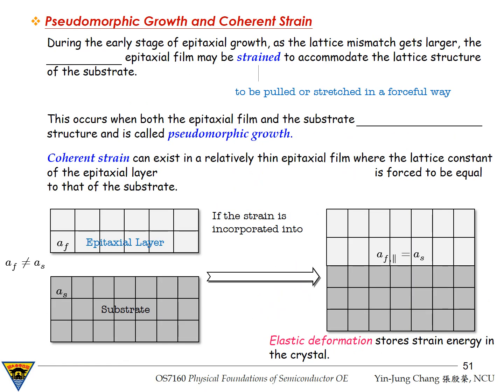Before delving into graded epitaxial growth, we need to fill in some gaps here, including pseudomorphic epitaxial growth, strain, and misfit dislocations. So far, we have discussed the ideal case of lattice-matched epitaxial growth, where the lattice constant of the epitaxial film is equal to that of the substrate. In that situation, the atomic rows line up perfectly, and no strain is introduced at the interface. But in many practical semiconductor systems, we do not have perfect lattice matching. The lattice constants of the film and the substrate are often slightly different. Now the question is, what happens when a material with a different lattice constant is grown on a substrate?